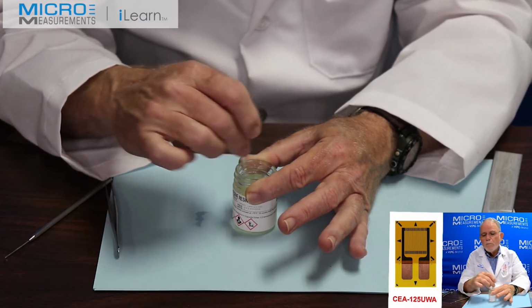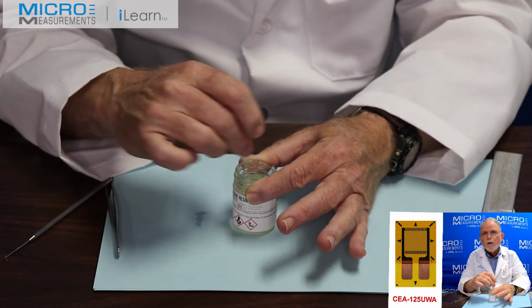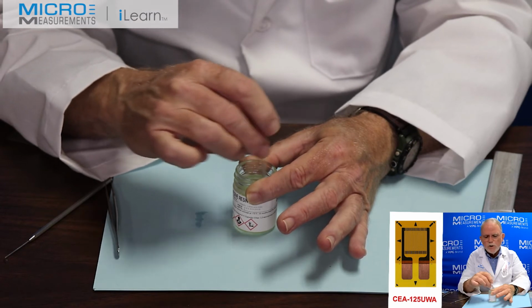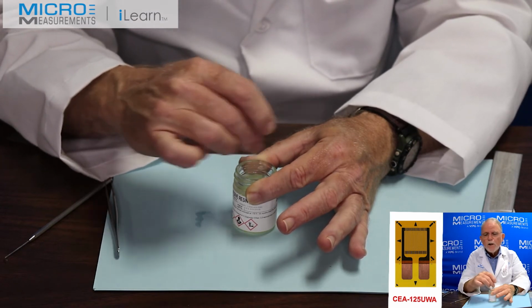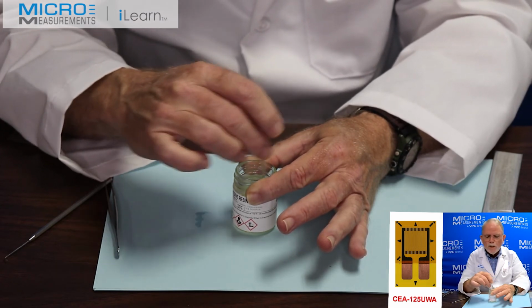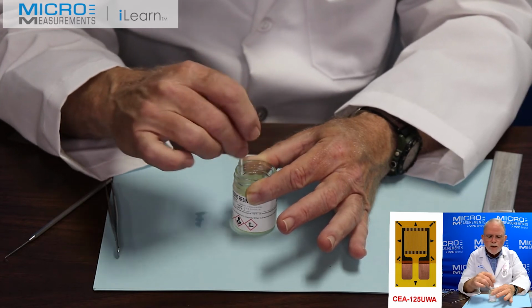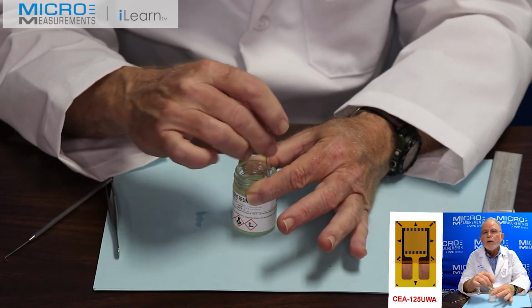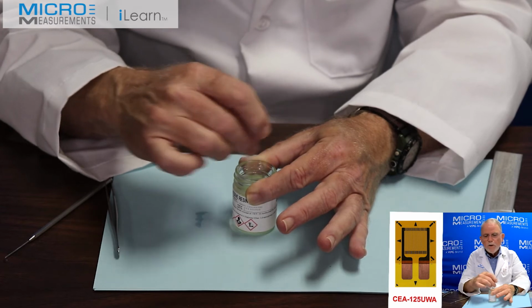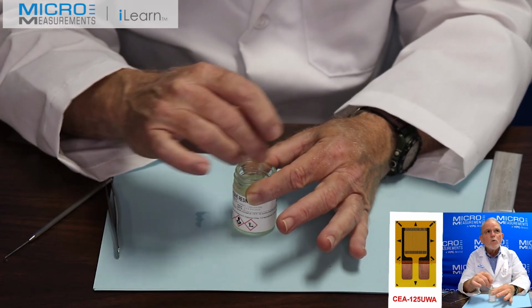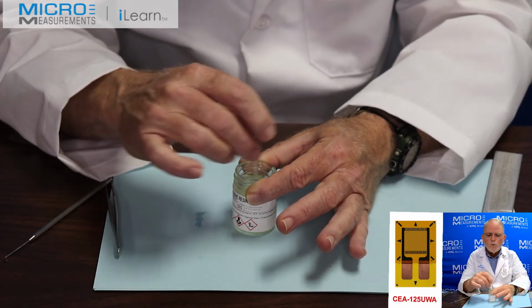And the reason for that, in this particular case with the AE-10, it's an exothermic reaction, and if we don't continue to stir it, the center of the jar would overheat or get higher temperature than the outside edges and might prematurely kick over the adhesive. So now I'm going to take this and I'm going to stir it for a full 5 minutes.